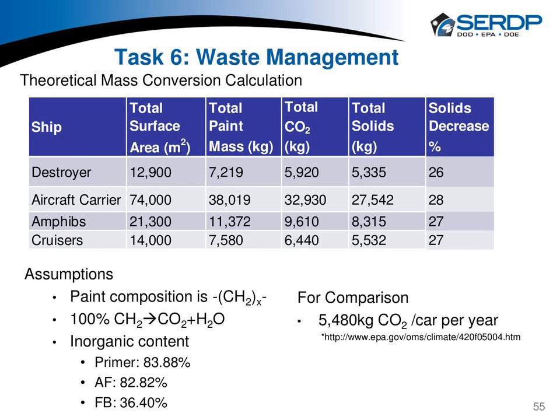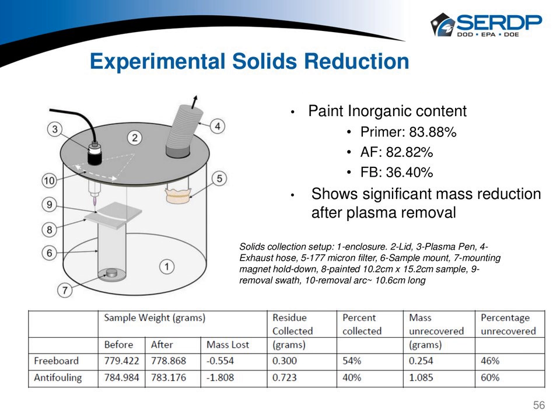Now, this was a theoretical calculation, but we also did it experimentally. So we had an enclosed chamber, rastered the plasma over the surface, weighed it before and after, both freeboard and anti-fouling, and measured the mass lost on the coupon. The rest had to go somewhere. The entire chamber was scrubbed to see what could be collected and what could not be collected. And very interesting, much higher concentrations, and this makes more sense. Somewhere on the order of 45 to 60% of the original paint mass is converted to gas.